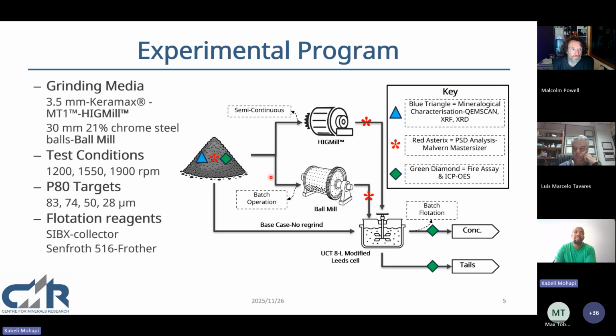In the grinding experiments, we achieved the P80 targets of 83 microns in a ball mill, and 74, 50, and 28 in the HIG mill. For flotation response, as our primary focus was recovery, not grade, we only used a collector and a frother. We used SIBX as a collector and Senfroth 516 as a frother.